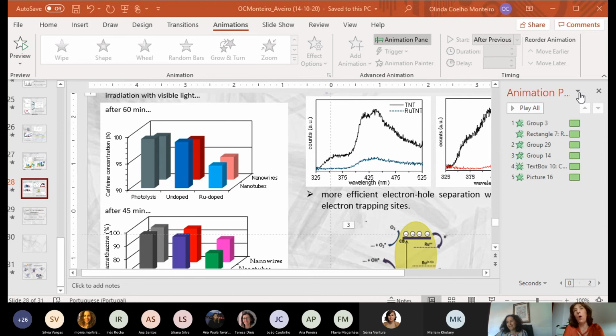This is a very interesting question. I showed some results where we had cobalt-doped particles that were exactly the same size as the pristine sample. But if you change the conditions, it's not true anymore. For us, it has been completely impossible to prepare doped nanofibers. Don't ask me why, because we use exactly the same conditions that we use to prepare titanate nanofibers. But if we put a dopant there, we always get wires or tubes, not fibers. We are not able to prepare long fibers with dopant. We try, and we have some hypotheses, but we are working on this.